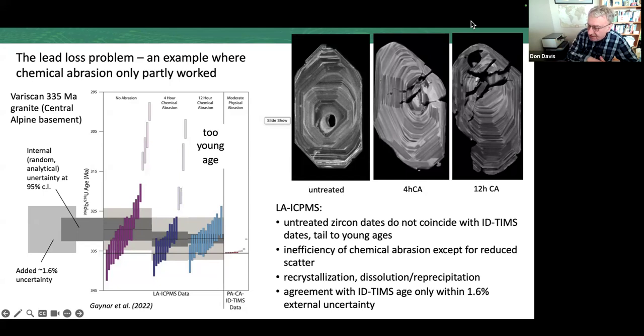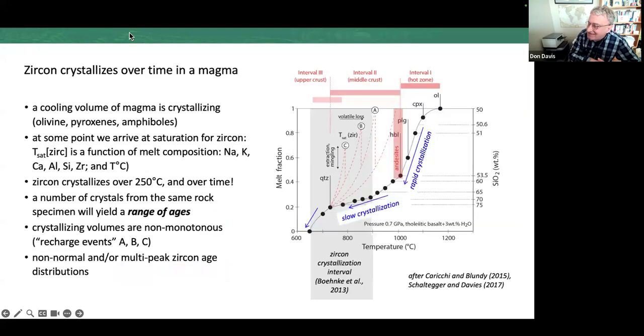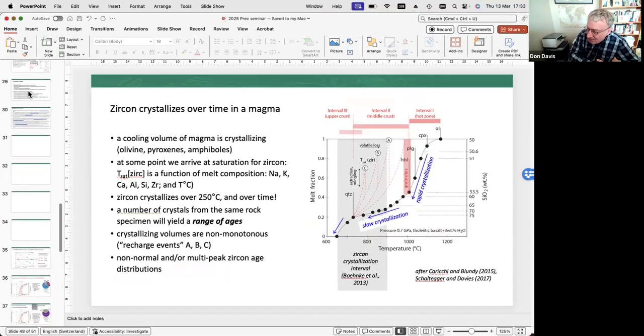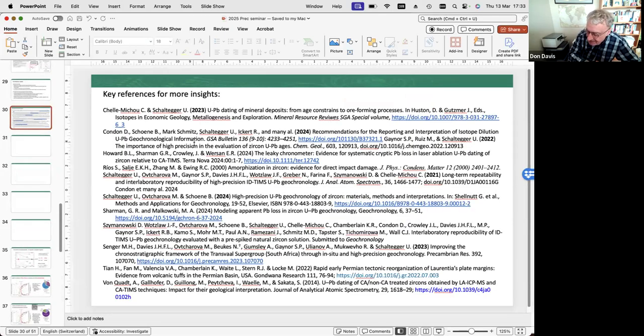We tried this on norite zircons from Sudbury, which are like 1,000 ppm. And if you anneal them, they can still be dissolved virtually completely within minutes because they're so damaged, and because even though you've recrystallized them and restored the Raman peaks, you've basically still got a mass of microcrystals with a lot of potential surface area to interact with the dissolving fluid. So it doesn't completely remove the damage. And annealing it again, I don't think would do anything. Basically, it probably very quickly goes to its most stable state.